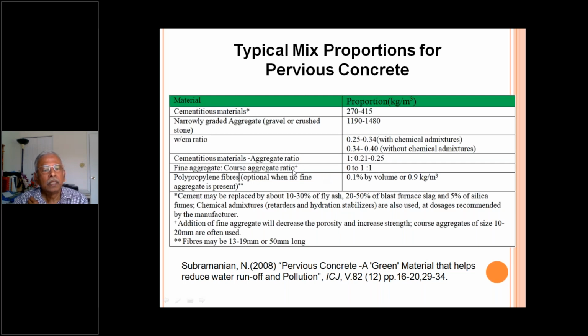Fine aggregates are normally not used, and in some places they have also used polypropylene fibers, and fibers may be 13 to 19 mm or 50 mm long. Of course, as I told you, the addition of fine aggregate will decrease the porosity, and hence it is not used, but in some places it can increase strength. And coarse aggregate size, as I told you, 10 to 20, but normally adopted is 10 to 12 mm.